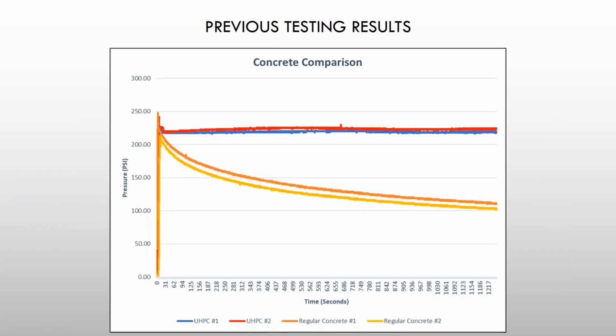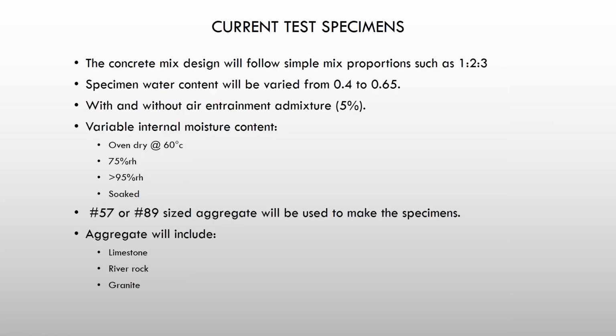These are the test results we achieved from those 4 test runs. The blue and the red lines up at the top are the UHPC. As you can see, the pressure did not degrade over the 20-minute period, while the normal strength concrete decreased in pressure.